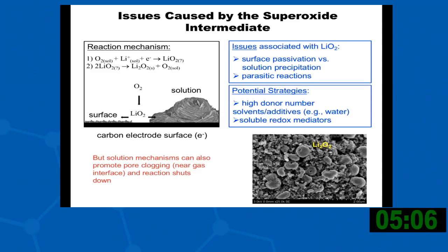and also block the transport of lithium ions. And this is a SEM picture of an electrode formed by a carbon called Super P, which is about 100 nanometer spherical ball particles, and you form an electrode by putting a binder together to hold everything together, and you can see that there are pores about the same size as the carbon particles, about 100 to 200 nanometers. And then you form these massive micron-sized toroidal structures of lithium peroxide on them, and so you can easily see how that becomes blocked.